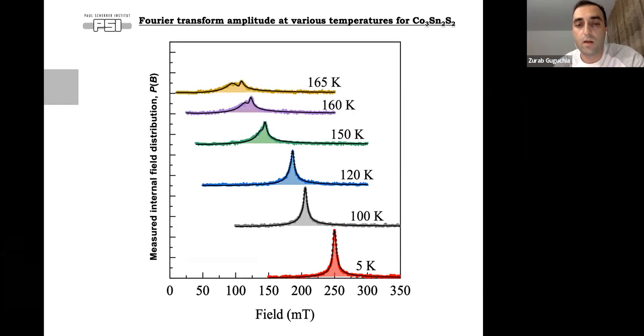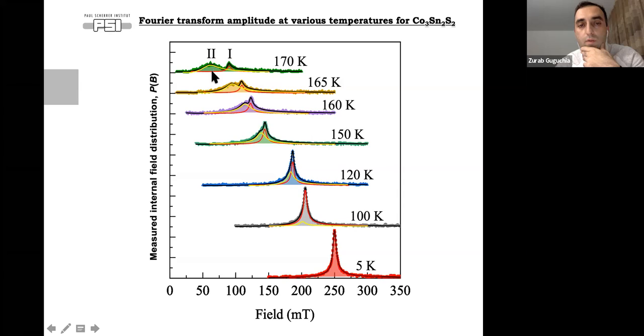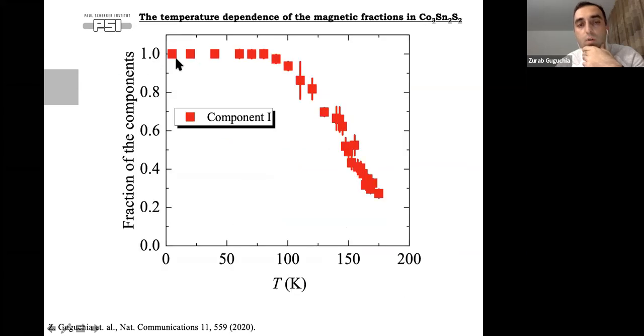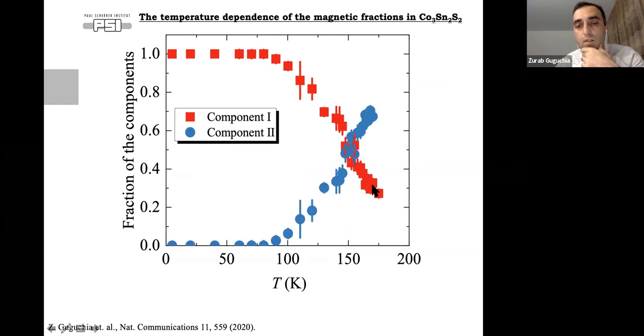So if I record these spectra, this is a Fourier transformation of the time spectra, and this is exactly the measured field distribution. At the base temperature, you have a narrow signal, so you have more or less homogeneous fields. And then when you increase the temperature, you have the evolution of a second peak, which then becomes more or less dominant. If you try to model this data, you see that we need to include the second component already from 100 Kelvin, and then this takes the majority of the fraction if you go close to the magnetic transition. Now if I plot the fraction of component 1, you see it is more or less constant, and then you lose this component, while at the same time, at the cost of this red, you get component 2. And then it takes the majority of the fraction.